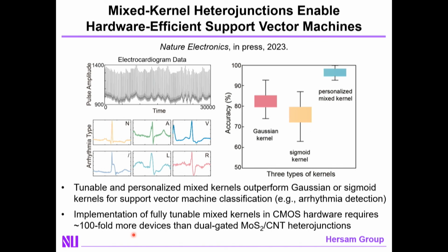We applied this to a particular use case, in particular doing classification of electrocardiogram data, where in particular what we were attempting to identify was arrhythmia in the patient. By personalizing the mixed kernel, which we can do just by changing the voltages applied to our device, we can push the accuracy for arrhythmia detection close to 100%, again in a manner where you have 100-fold fewer devices than CMOS. This makes it considerably more energy efficient, allows you to do the machine learning processing on site, for example, in the wearable device, as opposed to transmitting all the data to the cloud, which of course comes with a lot of wasted energy consumption. So edge computing is sort of enabled by this type of device.